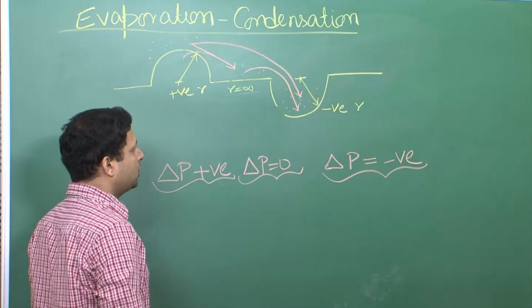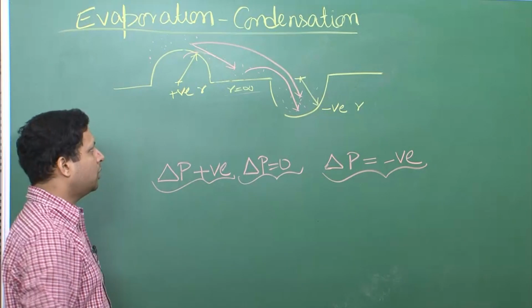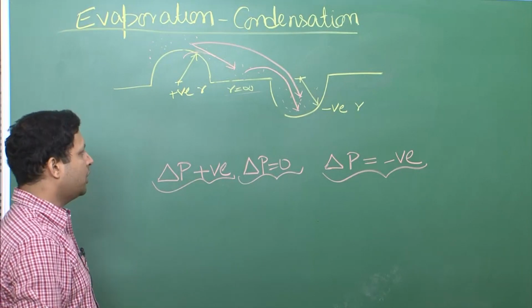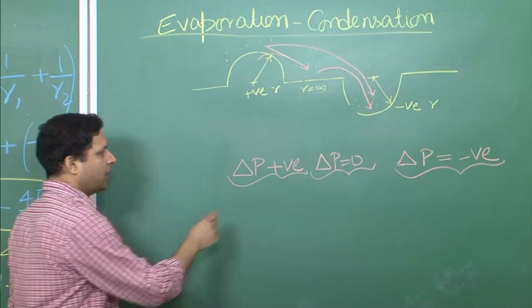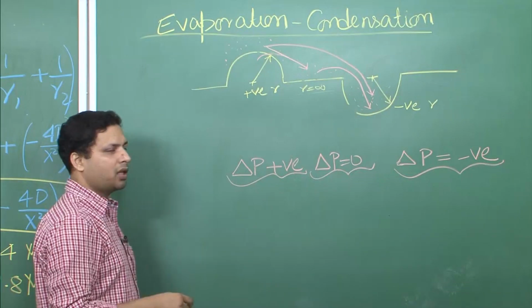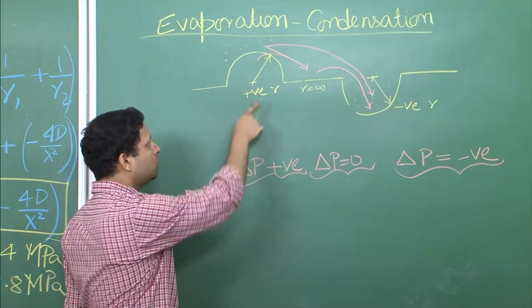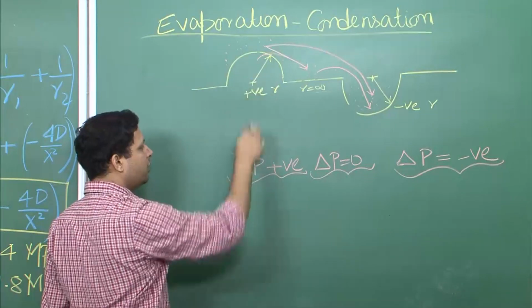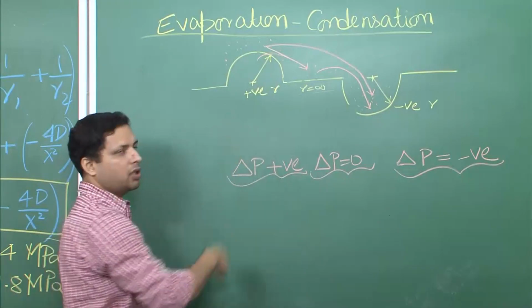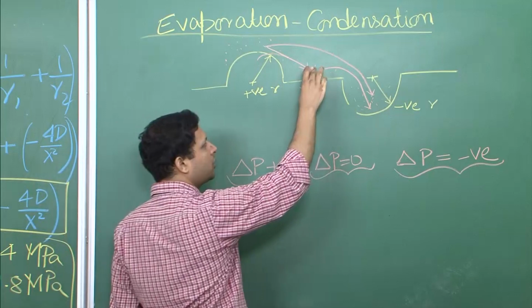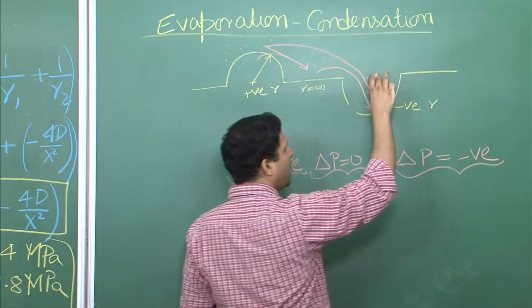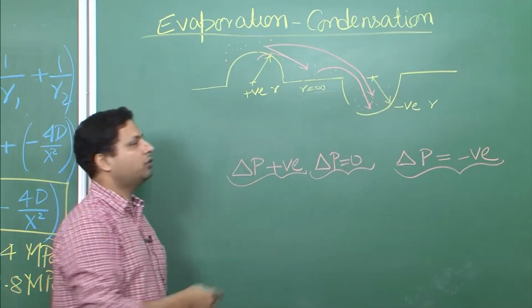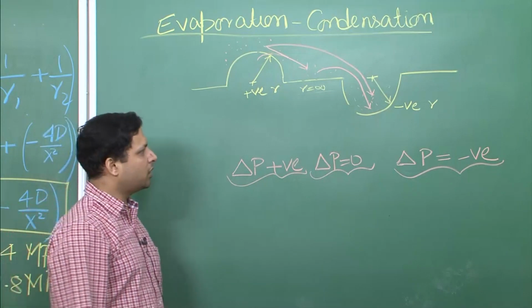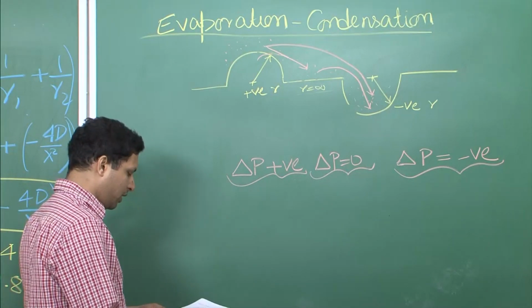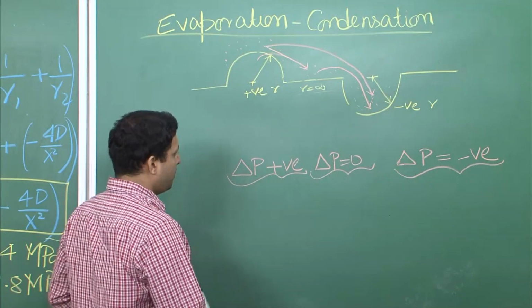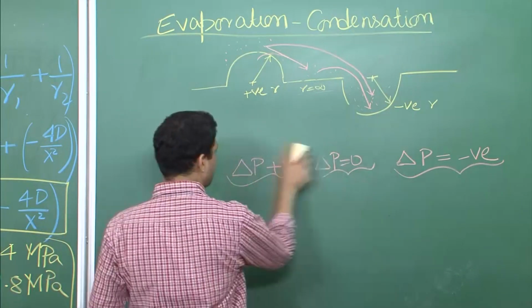So, this is the driving force behind your evaporation condensation: delta p is what is driving this, and delta p is again related to the radius of curvature. So, we have positive radius of curvature, we have positive delta p which is higher partial pressure, here somewhat lower partial pressure, and here even lower partial pressure, and therefore, you get this evaporation condensation mechanism that we see over here.